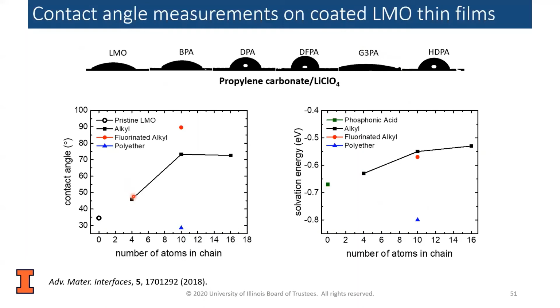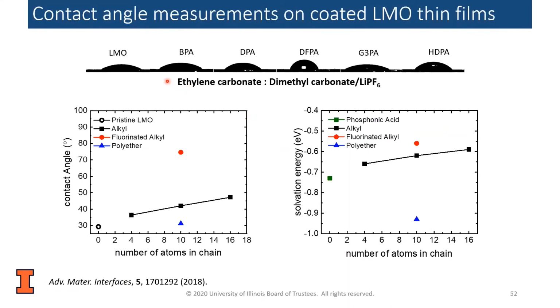And so you can see we'll have an increase in the contact angle for each of the increasing chain length alkyl groups, BPA, DPA, and HDPA. It looks like the DFPA, the fluorinated, has the highest. So it's probably the most hydrophobic of the solvents that we have. Next, we have a more common combination, the ethylene carbonate dimethyl carbonate system with the LiPF6. This is what most of the examples I showed earlier in the talk used as the solvent system. We can see we get a pretty linear increase in contact angle with increasing alkyl chain length. We see the contact angle is once again the greatest with the DFPA.